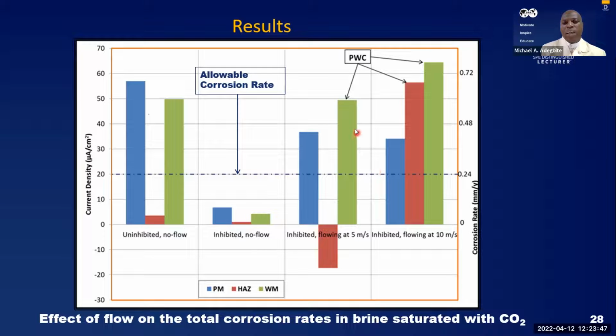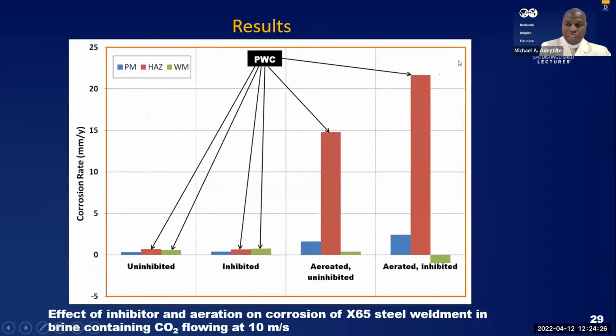In flow condition, we can see the weld metal is higher in inhibited, and when we even inhibit or run flowing at a higher rate, that's 10 meters per second, higher than a typical field situation, we can see the pronounced preferential weld corrosion. That is, the rate at which the weld metal and the heat affected zone corrode is higher than that of the parent metal. And that's essentially what we have in a